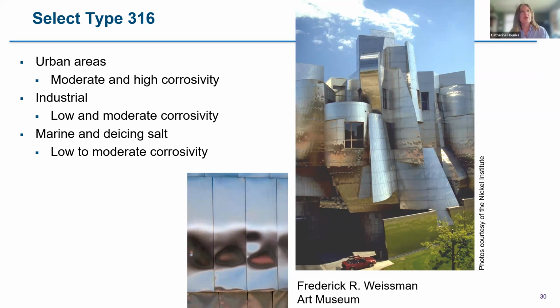316 is the better choice if you have a bit more pollution and you have low to moderate levels of salt exposure. This is a museum with a 316 exterior, and I took that picture from a highway bridge. The panel close-up was the panel closest to the roadway, and right by the crevices, because this was 316, you can see a little bit of discoloration, not much. It would have been easily cleaned off, but otherwise it's held up well, other than some dirt streaking.